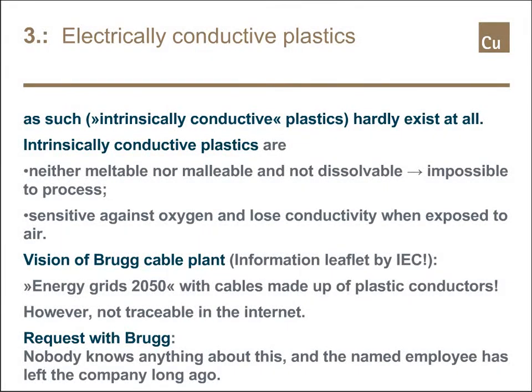Actually, they are not meant to be used as electrical conductors. They are used for applications where a tiny little bit of conductivity already suffices to serve a certain purpose, for instance, shielding. Intrinsically conductive plastics, where the plastic itself is conductive, are neither meltable nor malleable, and they are not dissolvable, so they are impossible to process. They are sensitive against oxygen, all of them, and they lose conductivity when exposed to air.